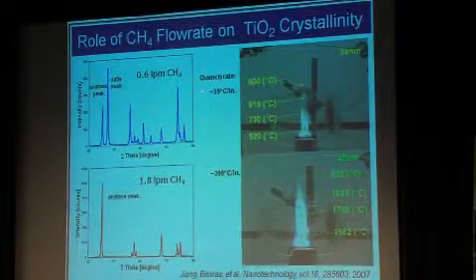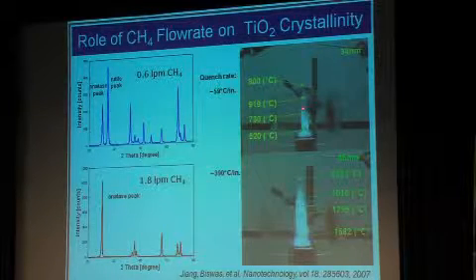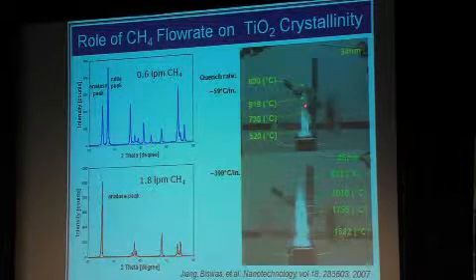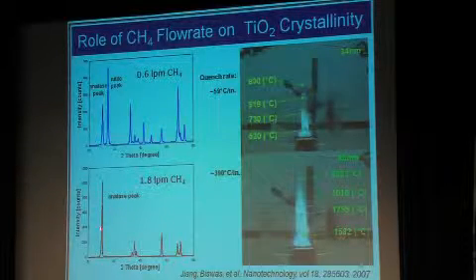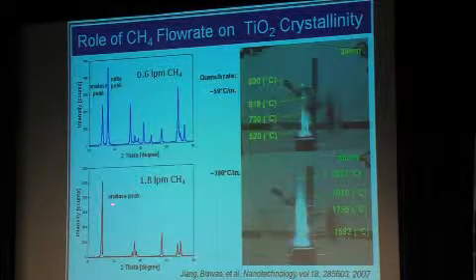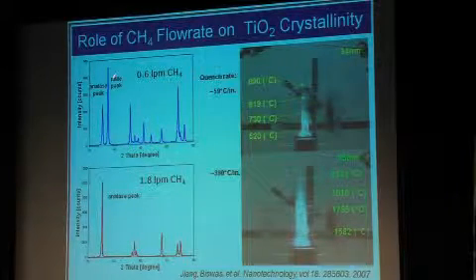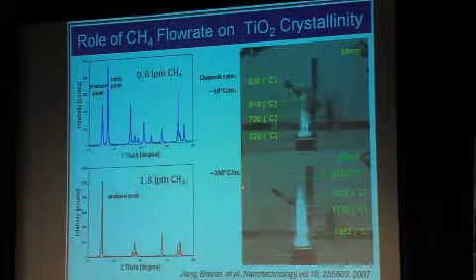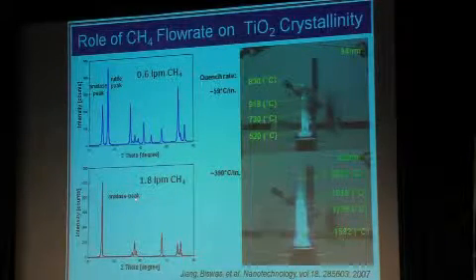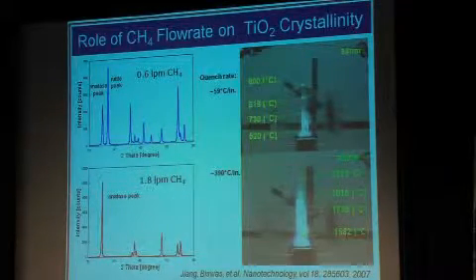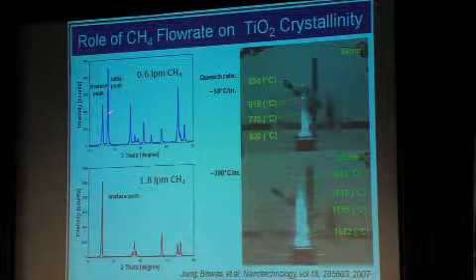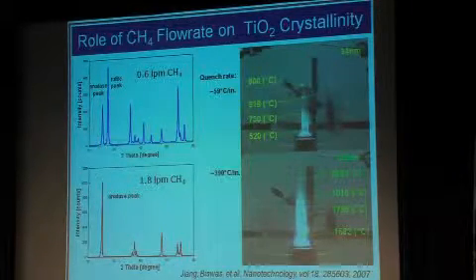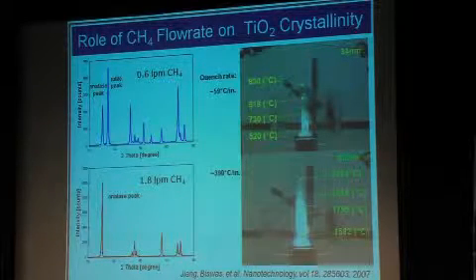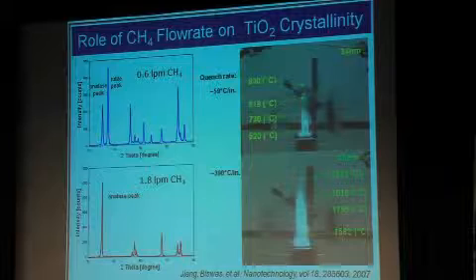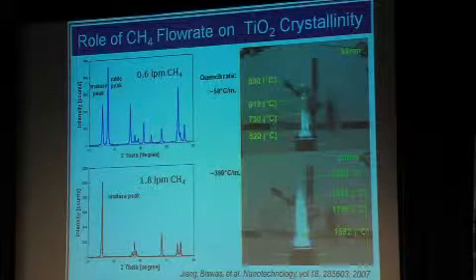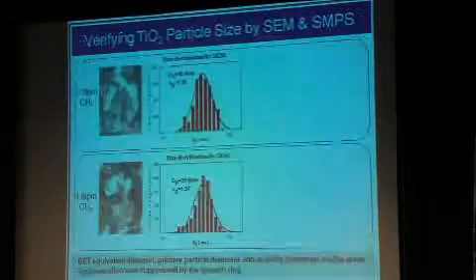By controlling the quench rate, this is the rate at which I'm cooling down the gases at the exit of the flame. With a very high quench rate, I get what is known as the metastable crystal phase, anatase. This is the stable crystal phase, rutile. But by controlling this, if I suddenly quench it, I can sort of preserve the anatase peak and get a pure, this is a 100% anatase sample. Or I could play with the temperature gradient and get a mix of anatase and rutile. So this understanding then allows me to get different mixes of crystal phases, get highly pure crystal phases, again, depending on the application or depending on what I want to do with them later on.